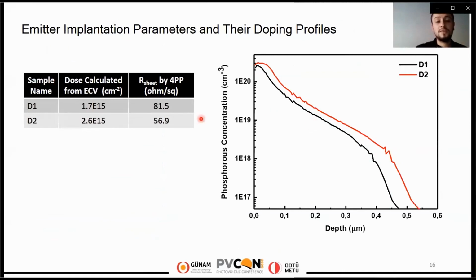Here you see the doping implantation parameters. We apply 2 doses in our cells that you will see in the coming slides. D1 and D2 correspond to the doses, and the sheet resistances were measured by four-point probe as 81 and 57 ohms per square respectively, and their corresponding doping profile curves are given on the right side. It was measured by the ECV method, electrochemical capacitance voltage. Of course, the higher dose results in a deeper junction and higher peak concentration at the surface.